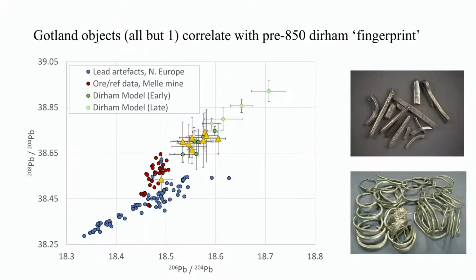Okay, so the material that we analyzed from Gotland plots this way here. And you see it has larger error bars because we did it by nanosecond laser ablation. But the interesting thing is that all the artifacts, except for one, all the artifacts fit with this early Islamic signature, so pre-850 if we go by the dirham models.